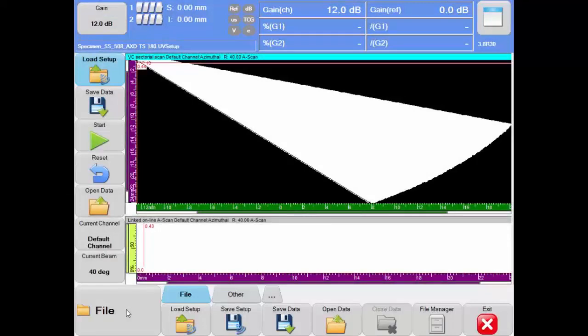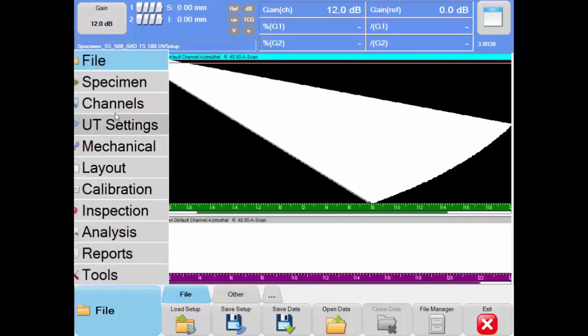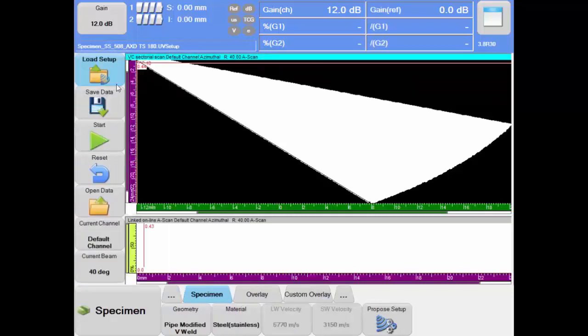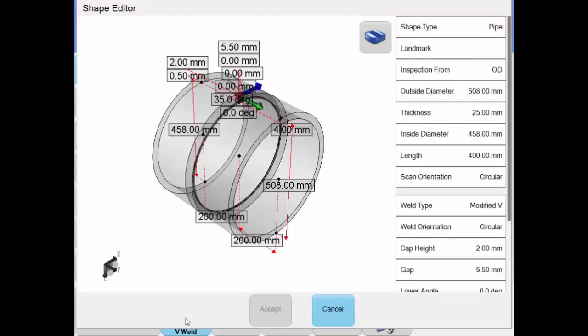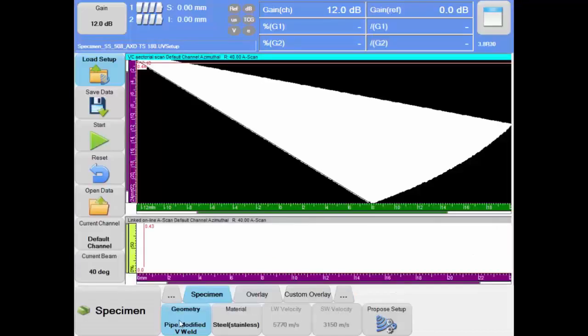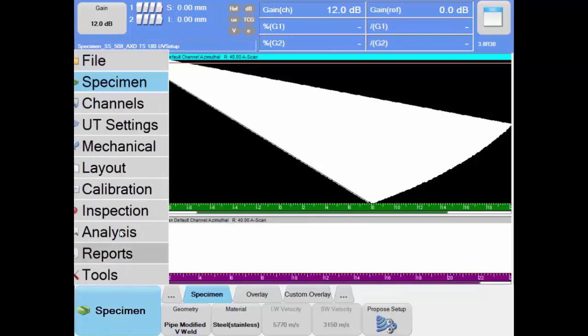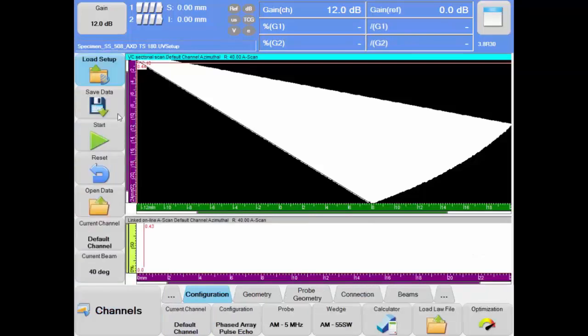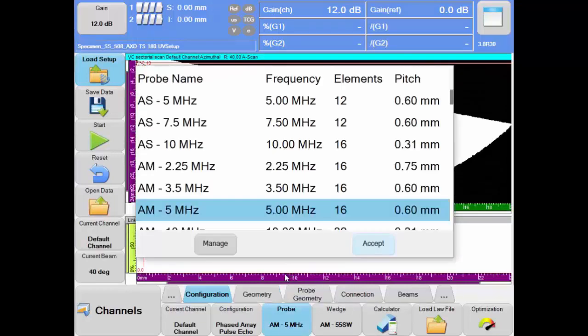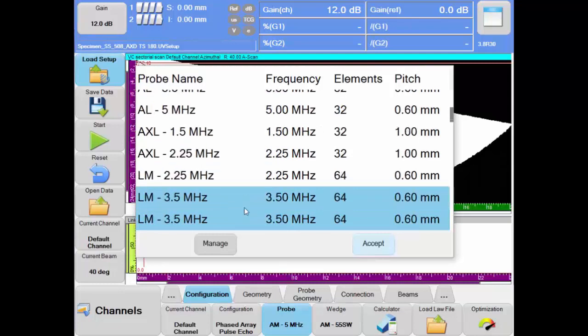Let us look how the onboard Ultravision Touch calculator handles the definition of focal law groups with various refracted angles and skew angles. The specimen has already been defined. It is a 20-inch diameter stainless steel pipe weld with a wall thickness of roughly 1 inch or 25 millimeters. In this example, we are using one of the standard Zetec matrix arrays at 1.5 MHz, but this time in a pulse echo configuration. We can load the probe parameters from the database.